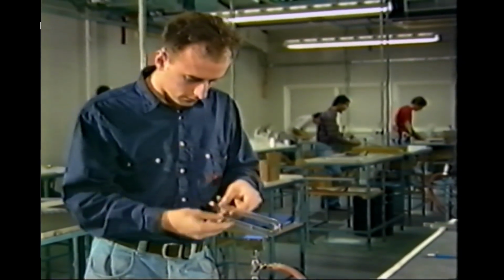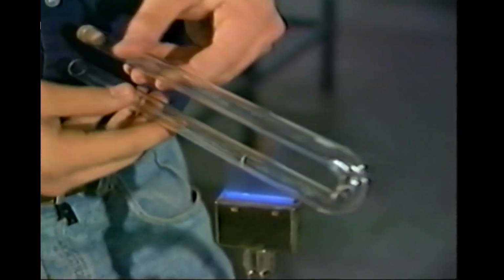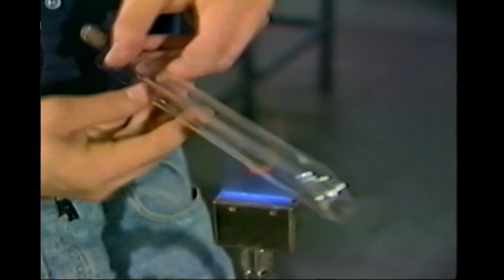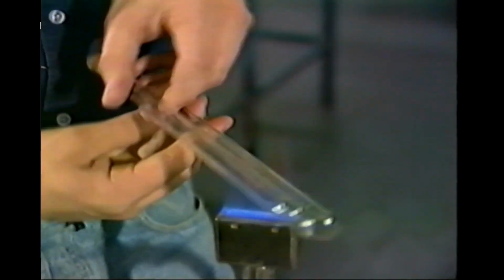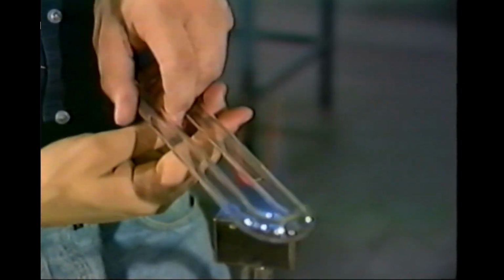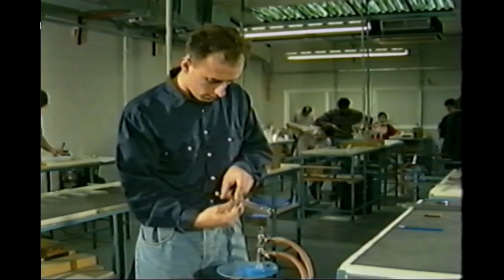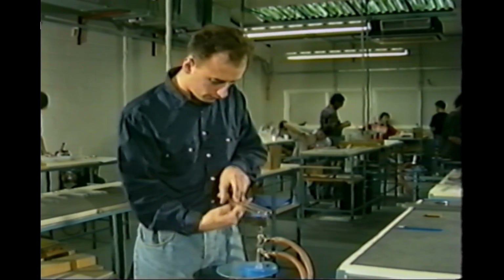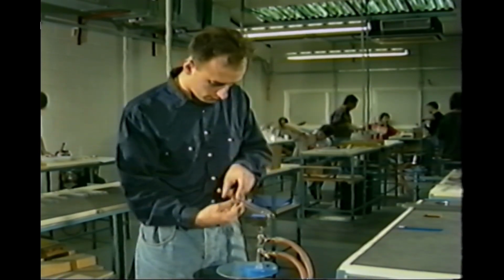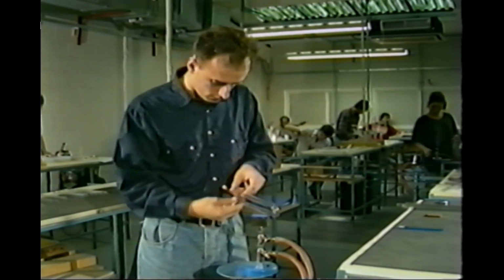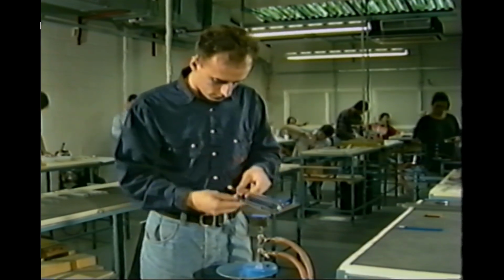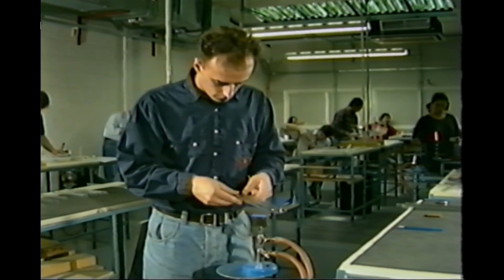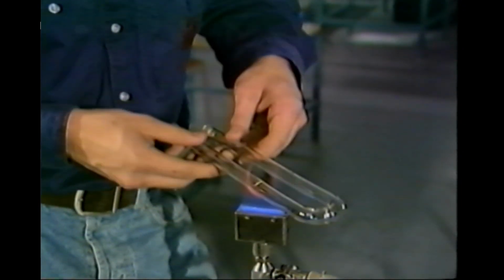Hold the two side arms near the ends and with the mark central in the flame, with the melt area 2 diameters wide, fully rotate the tube back and forth to produce an even melt around the whole circumference of the marked tube, whilst trying to keep the other sidearm out of the flame as much as possible. Keep the tube horizontal throughout the melt process. When the glass is heated to the correct temperature, cease rotation with the mark uppermost and allow the bottom area of glass to melt longer.